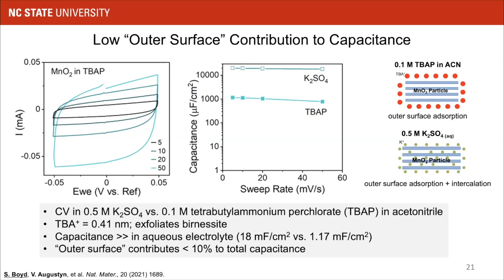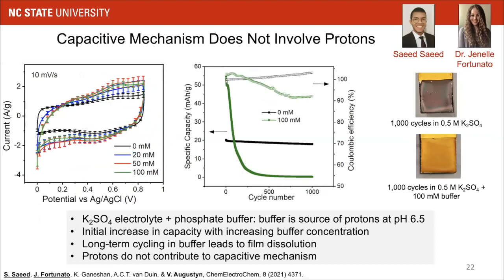And what we observed was that the capacitance is orders of magnitude greater in an aqueous electrolyte than in this non-aqueous electrolyte. So essentially what we see is that in the non-aqueous electrolyte, we must only have the outer surface adsorption process taking place, whereas in an aqueous electrolyte, we must have outer surface adsorption as well as intercalation coming into play. So we would estimate based on these results that the outer surface is contributing less than 10% to the total capacitance in the material.